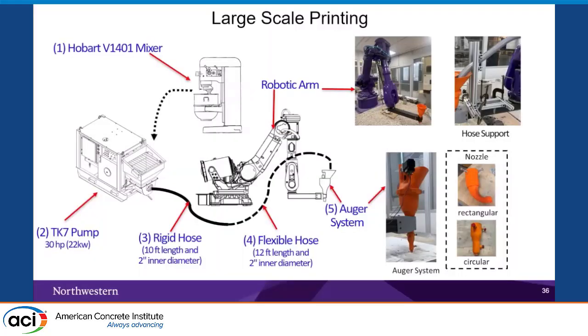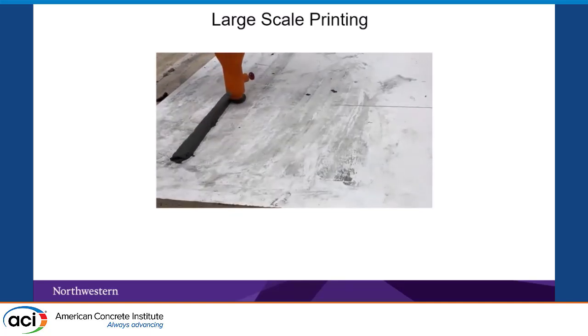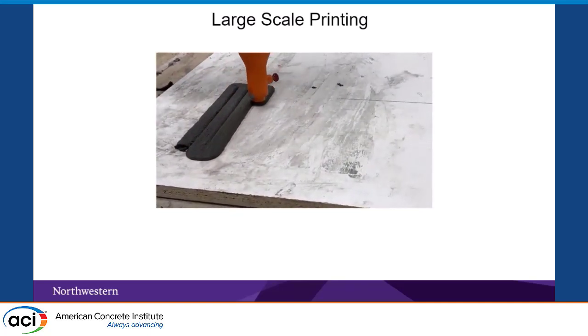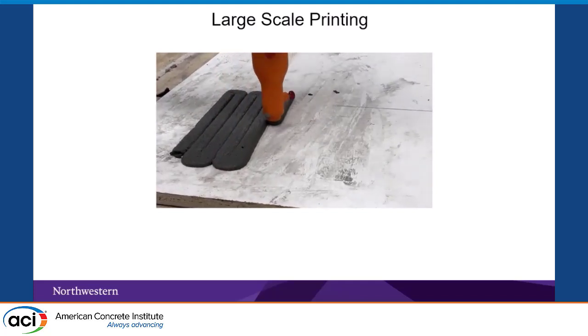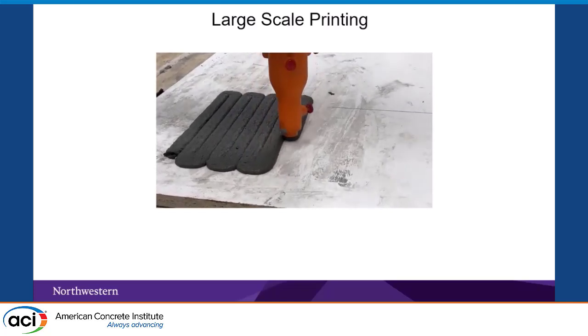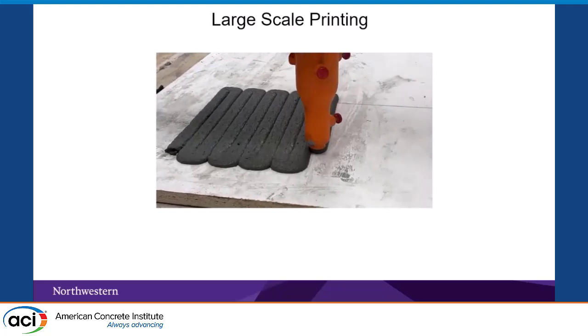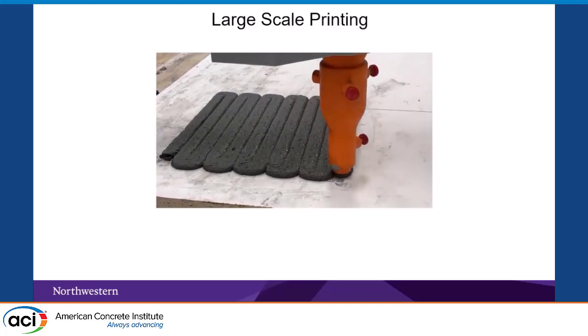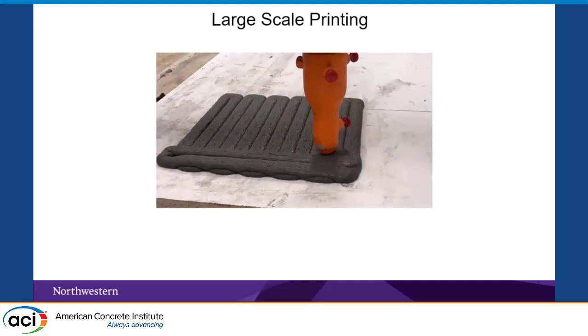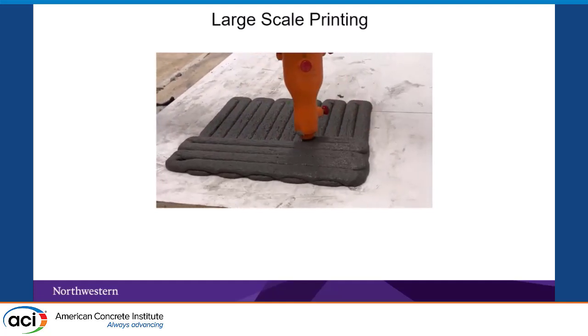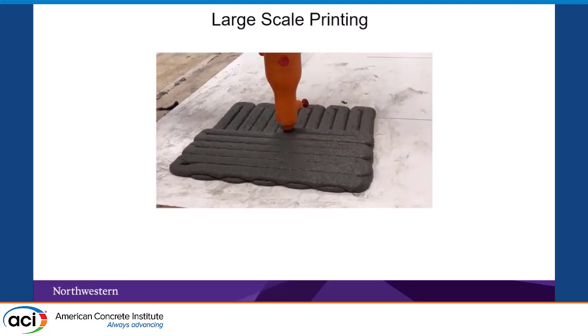In terms of future work, we need to scale up. We have this large mixer, which can be connected to a piston type pump, and then we can deliver the material to the extrusion system and eventually print. Out of this, we printed slabs using the idea of laminates, where we can print in the X direction, the Y direction, plus or minus 45, and adapt this for slabs, especially two-way slabs, which for sure will maximize the bending capacity of these slabs. Here the speed of printing is 50 millimeters in length per second, and I think we can also increase this printing speed.